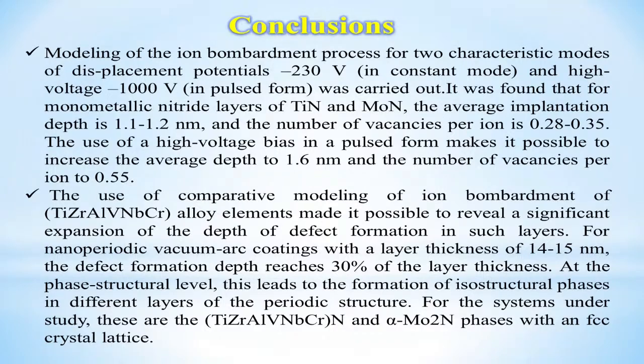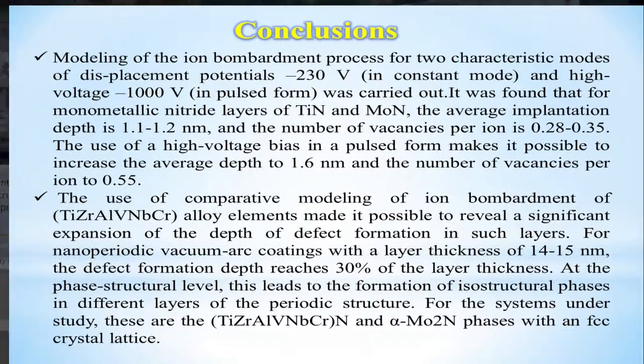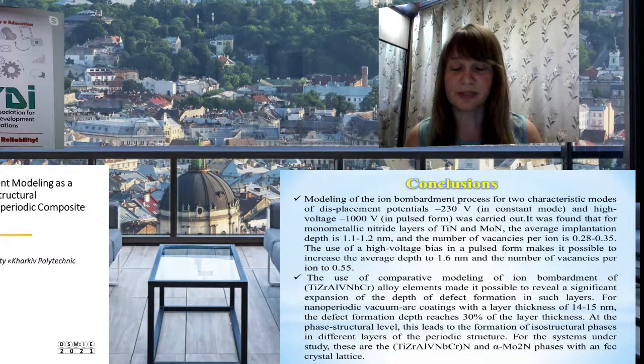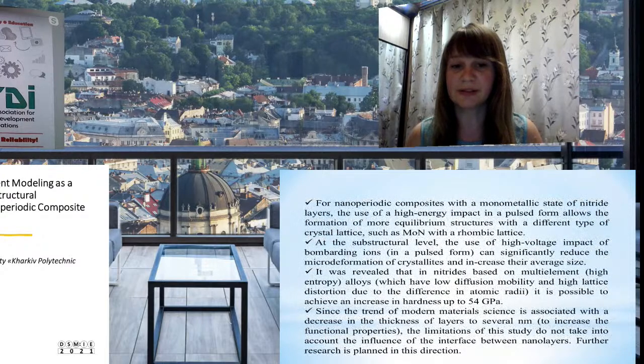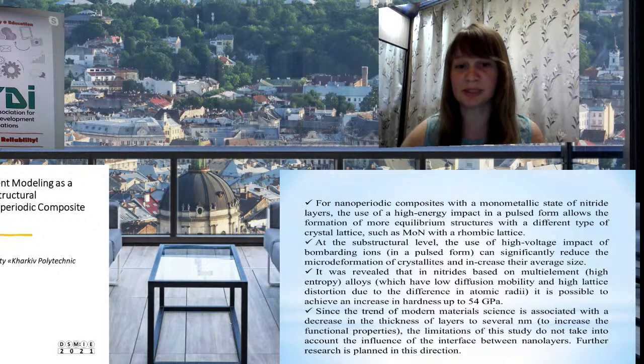Summing up, it is shown that for nanoperiodic composite coatings with the monometallic state of nitride layers, the use of high energy impact in a pulse form allows the formation of more equilibrium structure with different types of crystal lattice, such as MoN. The next slide. On the substructural level, the use of high voltage impact of ions can reduce the microdeformation of crystals and increase their average size. It was revealed that in nitride based on multi-element high entropy alloys, it is possible to achieve an increase in hardness up to 54 gigapascal.